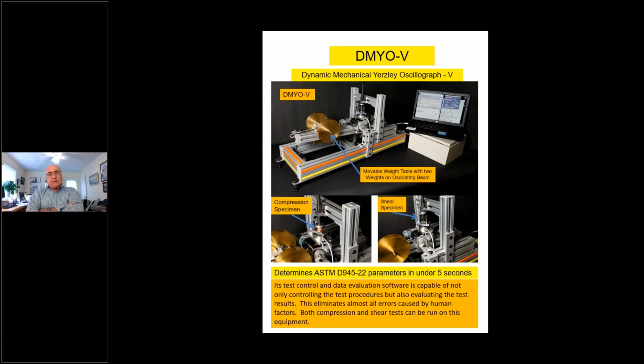In other words, if the sample has high delta or loss angle, that can take a little longer, maybe 5-6 seconds. If it is an elastic product, within 3 seconds, 2 seconds, we obtain the natural frequency and all the parameters of that particular sample. So that being the case, as we can take a look on the lower left corner, the compression specimen, and the lower right corner, there is a shear specimen. So basically, this is how we move.